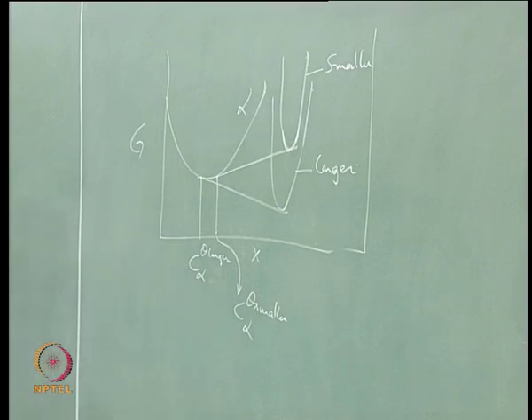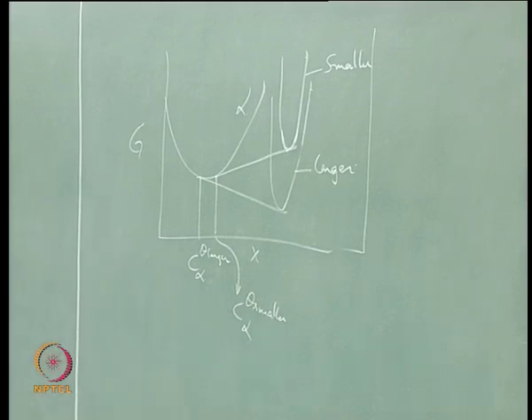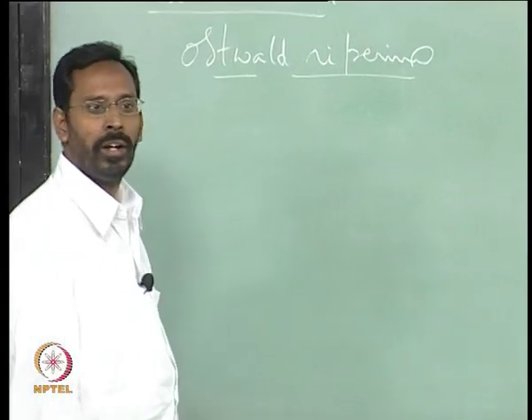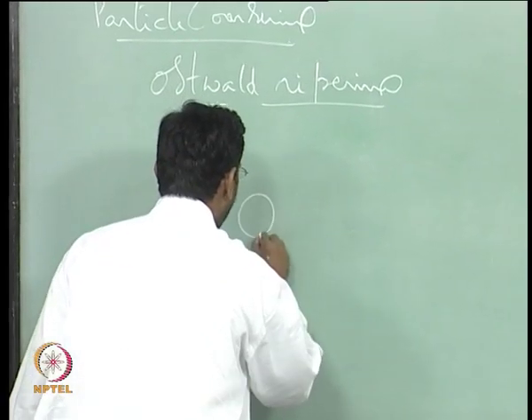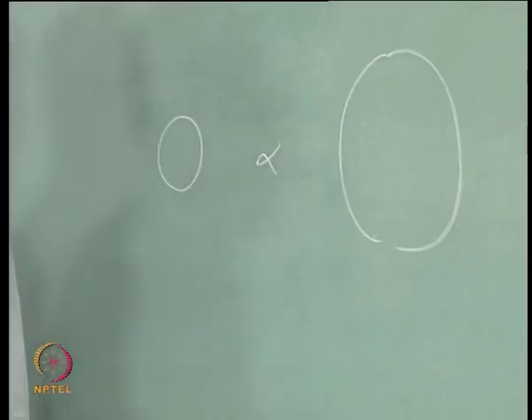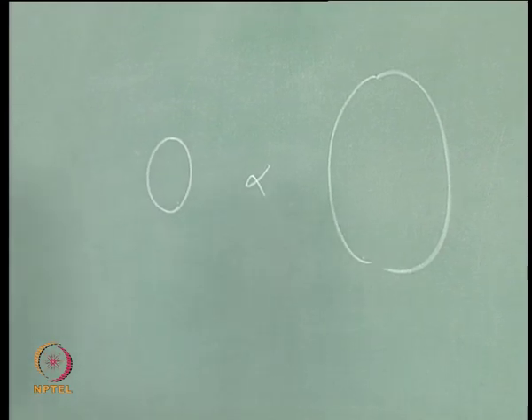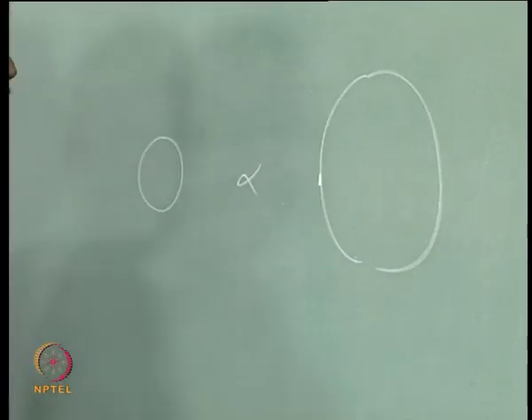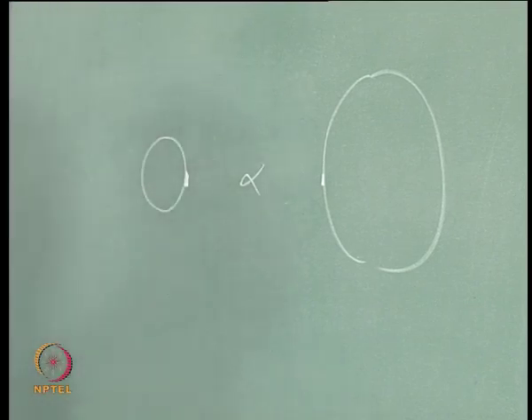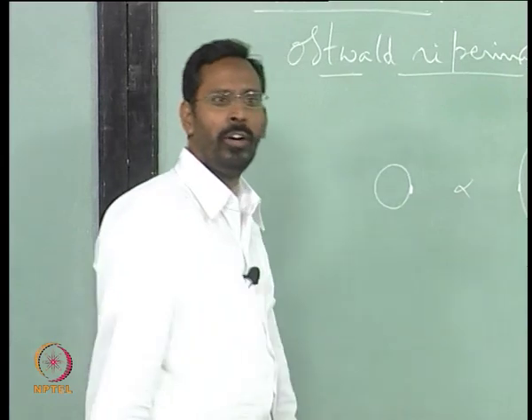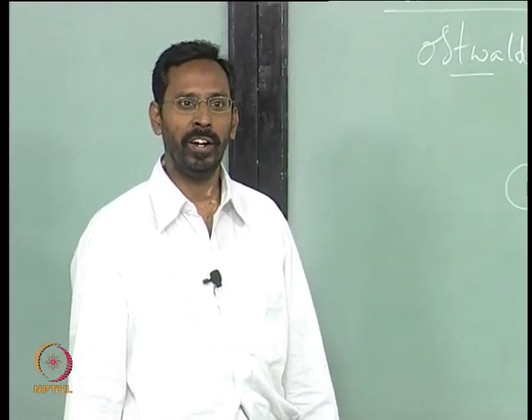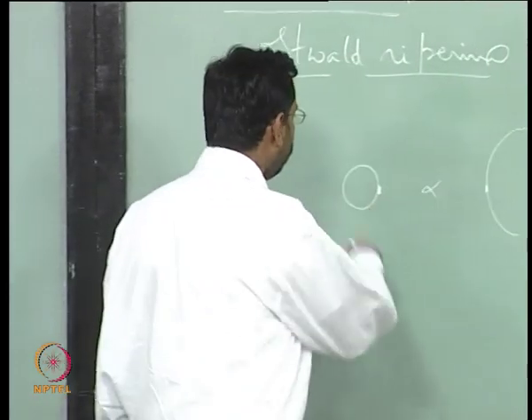The moment that is the case, if I now simply look at a smaller segment where you have one small particle, one large particle, and there is alpha in the middle, the composition of alpha which is just in front of this particle, and the composition of alpha which is just in front of this particle, is different, and which is higher? The smaller is the higher. So, if I now draw what is called the compositional profile, how would the compositional profile look like? The theta phase,